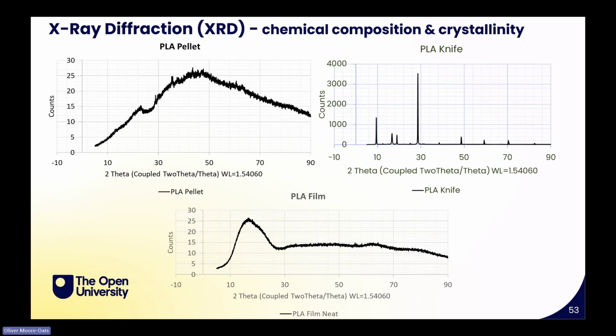Now, it's very important to say that if you can see some peaks there, if the peak is smaller or not as prominent, the polymer is basically less crystalline, so it has more amorphous regions, that means it's more elastic. If the peaks are high and very intense, the material is more stiff and hard. So for example, if you have a film, it's elastic, but if you have, for example, our knife, it's hard.